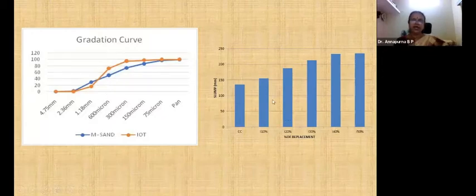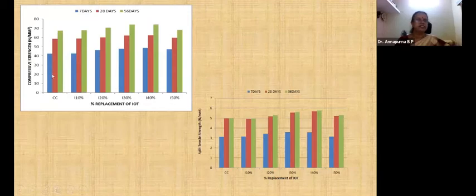This is the slump which we have found out. For conventional concrete and 10%, 20%, 30%, 40%, 50% IOT replacement, the workability increases with the presence of the IOT. This is the compressive strength for 7, 28, and 56 days for 10, 20, 30, 40, 50%. Compared to conventional concrete, it is the same up to 20%, and at 30% and 40% it shows an increase in the strength, and for 50% it shows a decrease. Even the split tensile strength shows a similar variation to the compressive strength.